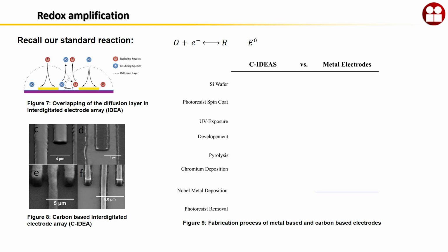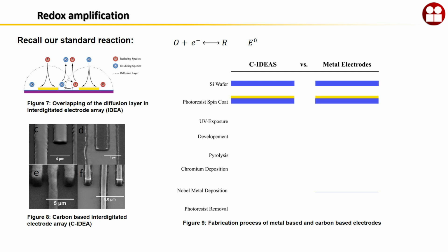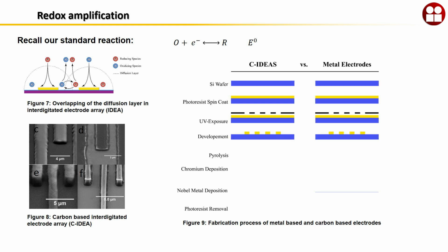And now I want to have a quick comparison between these 2 systems. Why we are interested to make these from carbon. Typically, the fabrication process starts with the silicon wafer, and then you coat a photoresist on a silicon wafer. At that point, you do the lithography, and you create like a pattern on the surface of your electrode, right? On the surface of your wafer. Now, you put this photoresist, pattern photoresist, into the furnace. In the absence of oxygen, you pyrolyze it, and you get some sort of carbon depending on the temperature that you're setting, right? But this system, this side, on the metal side, it is still going on.